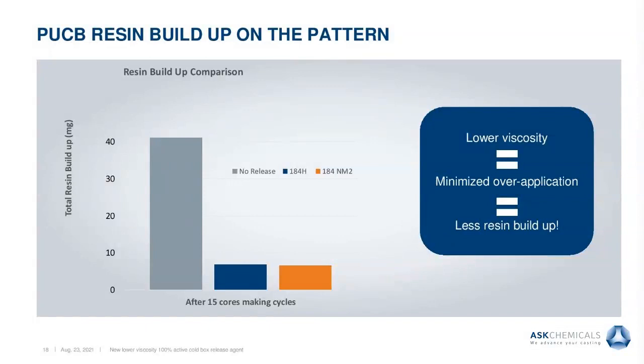Resin wipe-off consists of sand, resin, and release agent. After 15 cycles, 41.1 milligrams of buildup accumulated with no release. This is demonstrated with the gray bar on the left. The blue bar in the middle shows 6.9 milligrams of buildup accumulated with 184H, and the orange bar on the right shows 6.6 milligrams with 184H NM2. Lower viscosity equates to minimized over-application, which equates to less resin buildup.